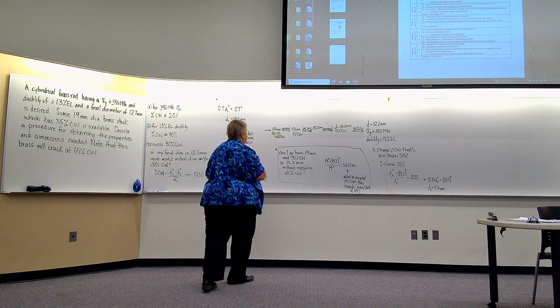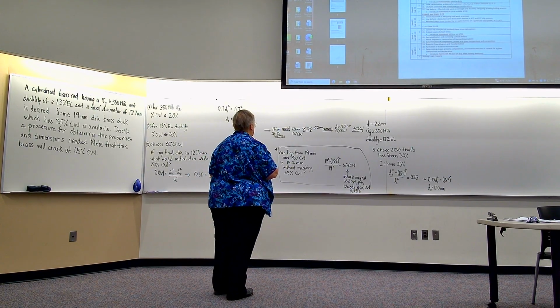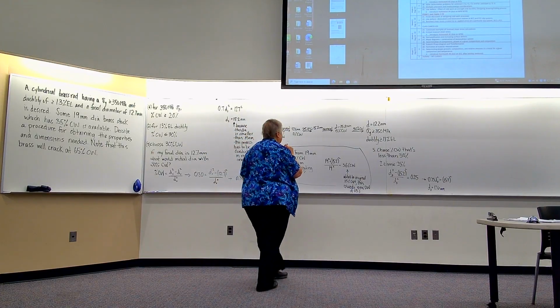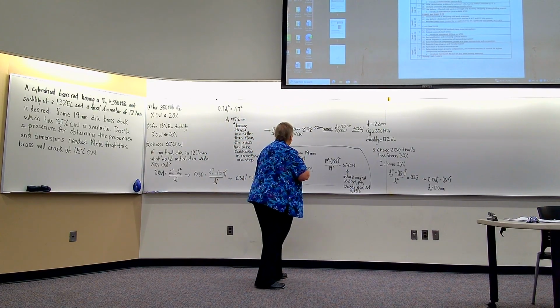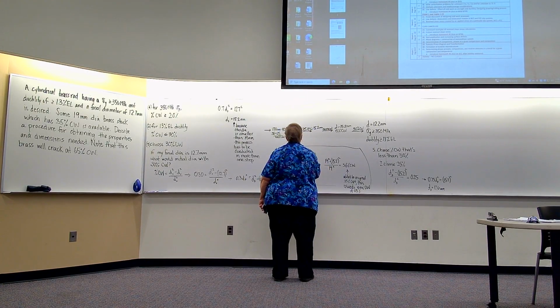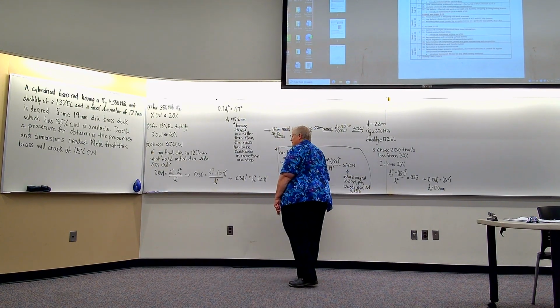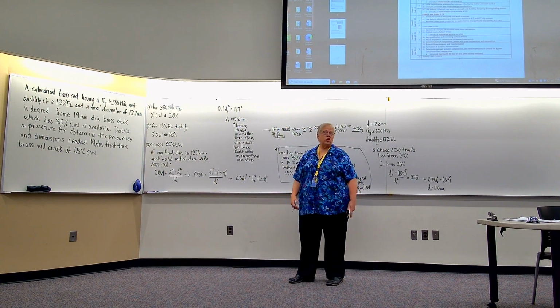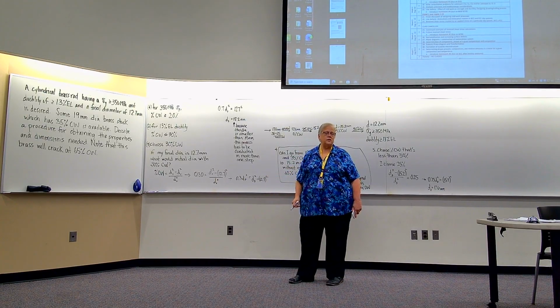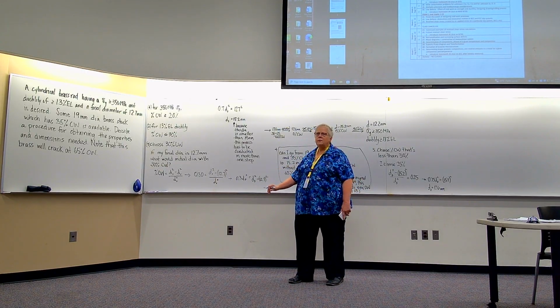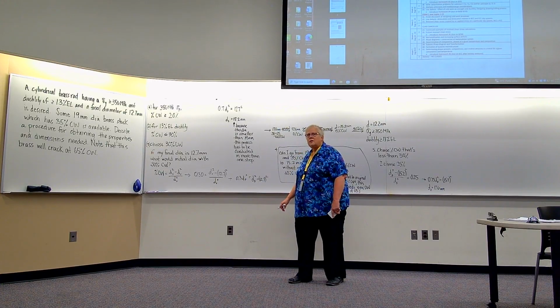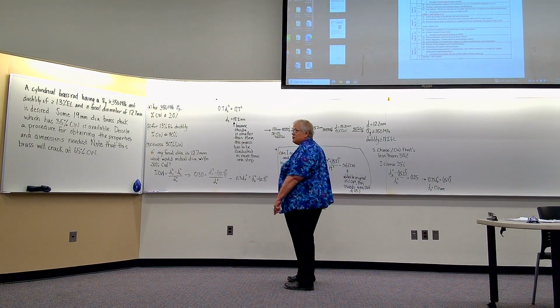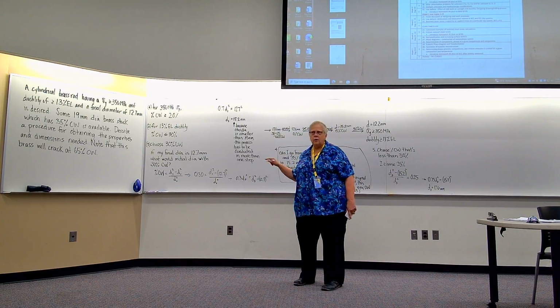Did I just do something twice? Yeah, I was going to say, how do you know it's 25? I just chose 25. Could you just anneal it at the very beginning of the process, and then do the one that we did? So what Alice suggests is, let's just get it back to 0% cold work before we do anything. And then we could do it in 2 steps, and that would be correct. Or you could do some cold work and anneal, more 25% cold work, anneal, the last amount of cold work, which was 30% cold work.